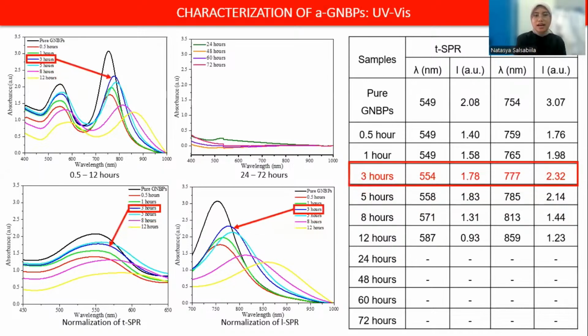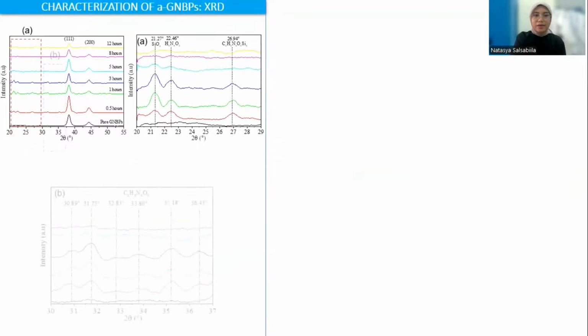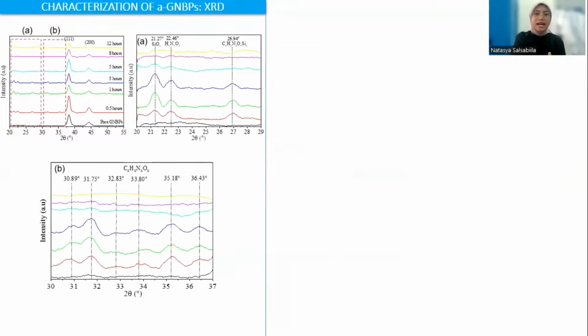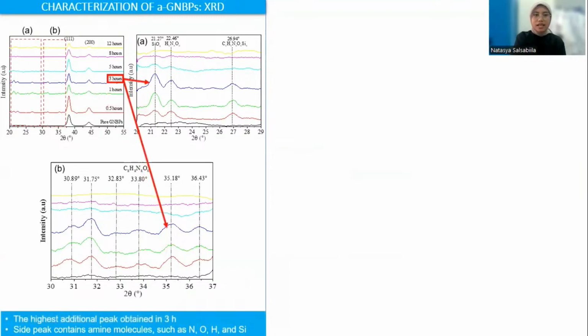Based on this result, the highest absorbance value is obtained at 3 hours. With over 12 hours, there is no peak anymore in the spectrum, indicating that there is no nanoparticle remaining as a side effect of over functionalization time. Yeah, this is the XRD results for AGNBPs. So based on this result, the highest additional peak is obtained at 3 hours, which consists of amine molecules such as Si, N, O, and H. Indicates that the highest binding reaction between amine groups and GNBPs surface is obtained at 3 hours.